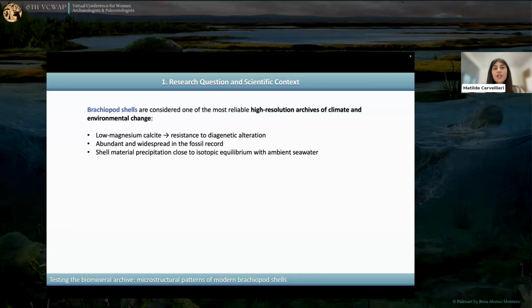Brachiopod shells are considered one of the most reliable high-resolution archives of climate and environmental change, as they precipitate a low magnesium calcite shell, which makes them resistant to diagenetic alteration. They are abundant and widespread in the fossil record, and they precipitate their shell close to isotopic equilibrium with the ambient seawater, with limited vital effects.